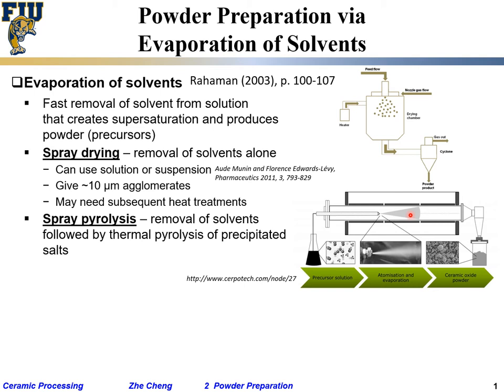The chemical reactions involved are called thermolysis, or pyrolysis — some people use either term — where the chemical compounds go through decomposition reactions. At the other end we collect the powder. This method can be directly used for production of powders; previous students used this method to directly synthesize carbide in the lab in one step.